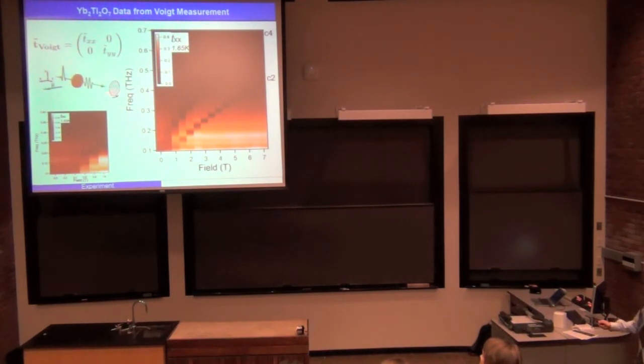And when the field is in the sample plane, like this, the light travels in this direction, then the spin will precess in this direction. So as a result, you don't really expect absorption in a circular channel. But instead, you expect the material to have absorption in a linear channel. So here we have TXX and TYY. Here I showed you data we measured in TXX at 1.65 K.